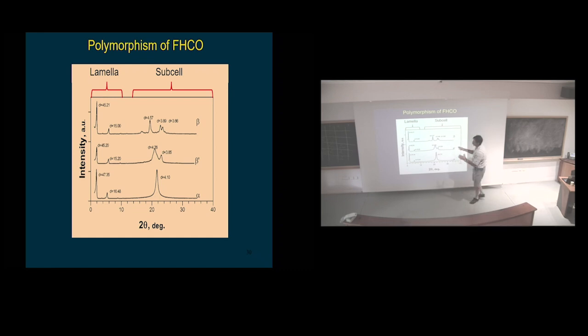But you look at that, you say, oh, they don't do indexing. You know how impossible it is to do indexing with this garbage? Impossible. Absolutely impossible. You have 4 peaks and they're all deformed because you have a multiple component system. So, bootstrapping, gentlemen and ladies. Meaning, you do the best you can. So 4.1, 3.8, 4.2, and here characteristic reflections for the beta form, 3.7, 3.9, and 4.6. And look at these nice ones.